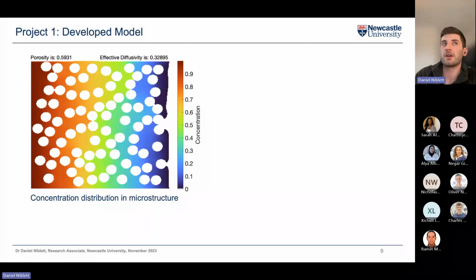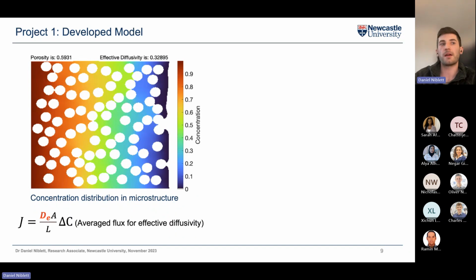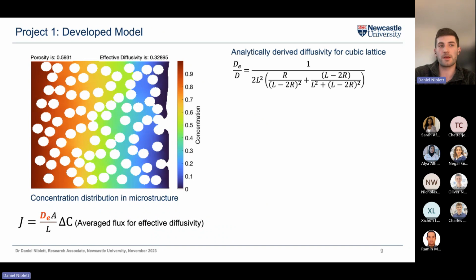So the colors that you see in here is I set a concentration of 1 on the left and a concentration of 0 on the right. And then by solving the Laplace equation, you get the distribution of the concentration inside the microstructure. And from that, you can essentially use Fick's law again to get the average flux over this structure, which then you can convert back into this dE here, which is the effective diffusivity. And that tells you how good your material is inside that block at conducting species, so chemical species, through that material. And what we want to do is we want to try and optimize that material.